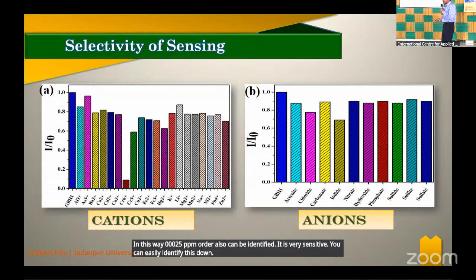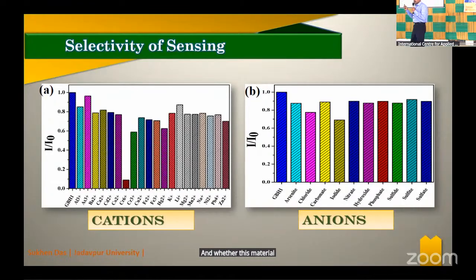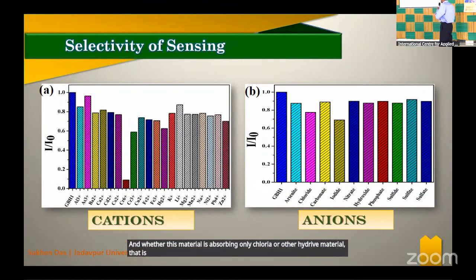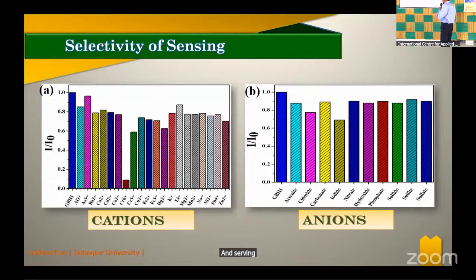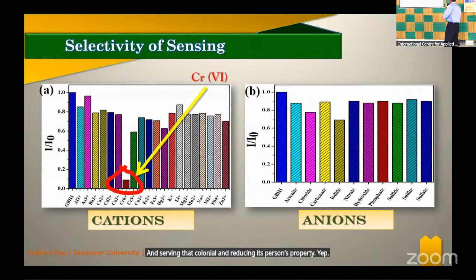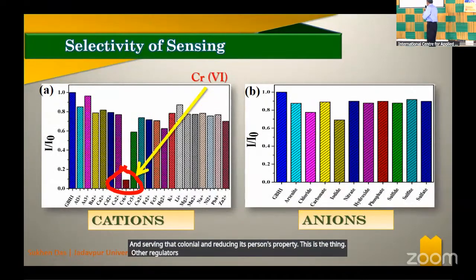And whether this material is absorbing only chromium or other heavy metals, that is why we tested this with other heavy metals. Other heavy metals, zinc, iron, cobalt, nickel, all we have used, but we have seen that this material is only absorbing chromium and reducing its fluorescence property.